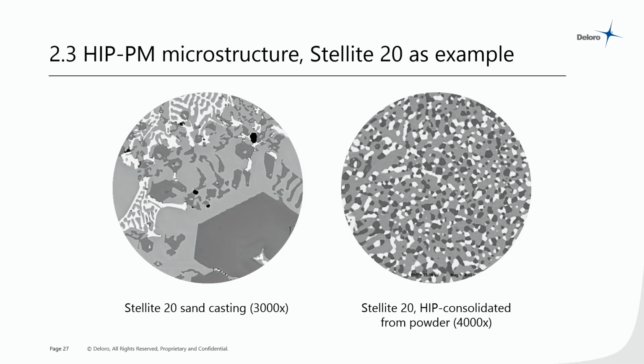And if you look at it, you'll see that you have a light gray cobalt chrome matrix. You could imagine that that's a ductile matrix. You have dark gray chrome-rich carbides, big blocky things which actually go into the picture. They're actually a spiny shape. And then you have white carbides, which are tungsten-rich carbides.